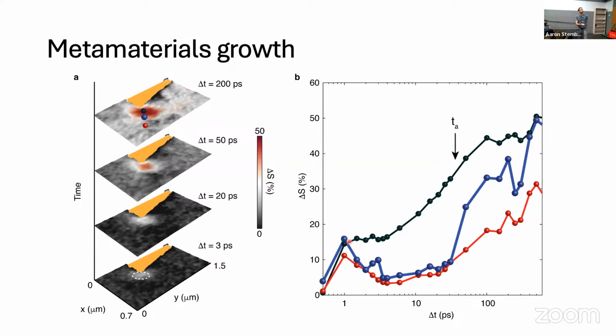The second thing is that if you look at some intermediate location between the edge of the antenna and the interior, you can see that first, the change in near field amplitude is tracking what you see in the interior of the film. And then at some time delay, there's an abrupt jump or increase in the signal when the domain reaches this location. So we believe that this metamaterial is anchoring the transition to specific sites, and this may be a nice way to intentionally anchor nucleation to target locations and monitor how the system evolves as a function of space and time.